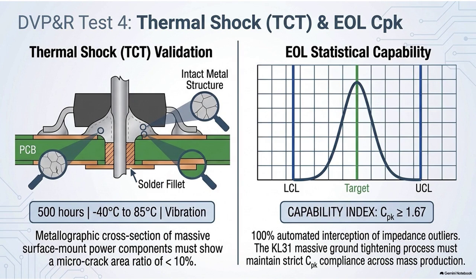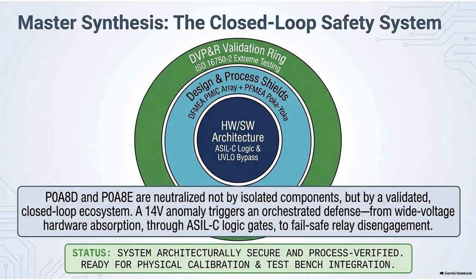In a severe thermal shock test, microscopic stress cracks will inevitably form. But the validation standard dictates that the cumulative length of those cracks must account for less than 10% of the joint's total cross-sectional area. So if a crack has propagated through 11% of the joint, the engineering team has failed. They have to go back, change the reflow oven temperature profile, perhaps change the geometry of the copper pad on the PCB, and run the 500-hour test all over again. They demand a process that is mathematically incapable of failing in the field.